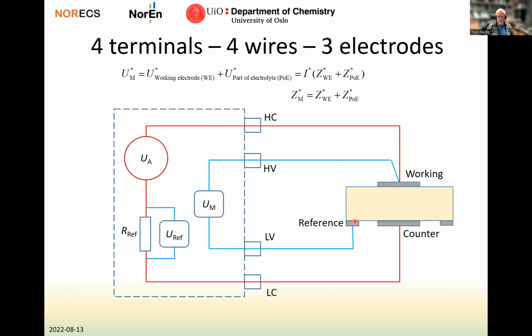There is no voltage drop in this electrode because there is no current running here. So this reference electrode picks up the voltage somewhere in here where there are current lines running between these 2 electrodes. So the measured voltage is now the voltage of the working electrode, this one here, and part of the electrolyte, part of the sample. And the impedance we measure is the impedance of the working electrode and part of the electrolyte.